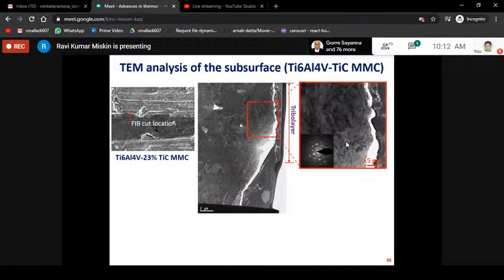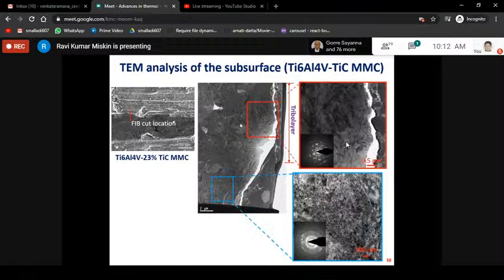So this is some interesting microscopy we did. This is a transmission electron microscopy. So what we did basically was we cut the wear track. There's a FIB cut, so basically you cut it with an electron beam. And how we cut it, the red mark on the left side image is basically the location where we perform this cut. So the darker contrast there is basically your tribolayer, and the lighter contrast is basically the wear track itself.